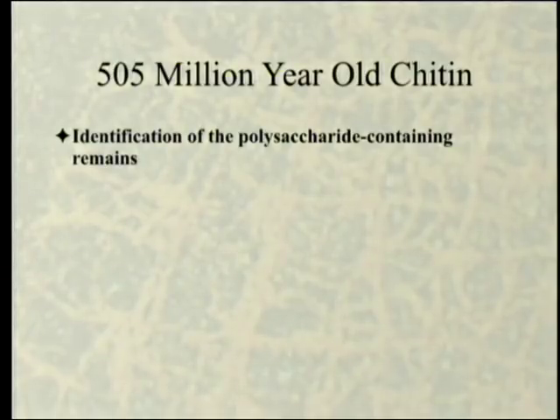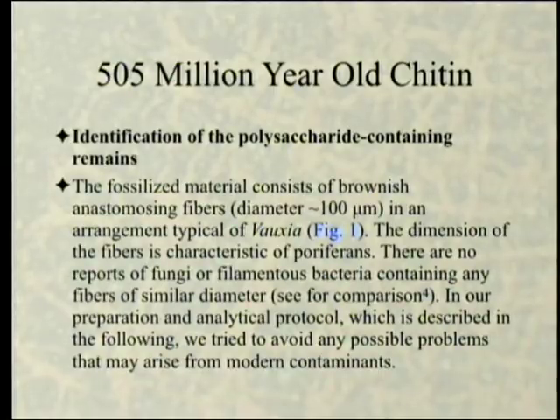Identification of the polysaccharide containing remains. This is what they're actually doing. The fossilized material consists of brownish anastomosing fibers, diameter about 100 micrometers, in an arrangement typical of Vauxia. And we'll look at that figure again. The dimension of the fibers is characteristic of porifera. There are no reports of fungi or filamentous bacteria containing any fibers of similar diameter. See for comparison reference 4. In our preparation and analytical protocol, which is described in the following, we tried to avoid any possible problems that may arise from modern contaminants. So they've been very careful, and they're getting only the sponge stuff and not something else, okay?